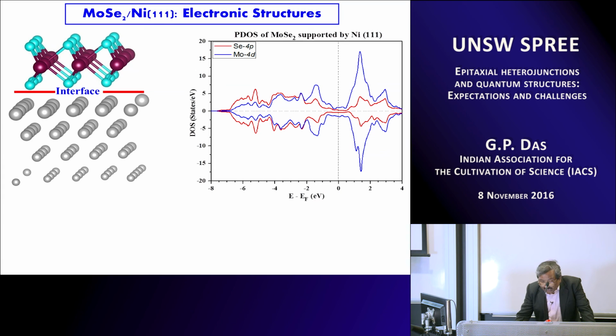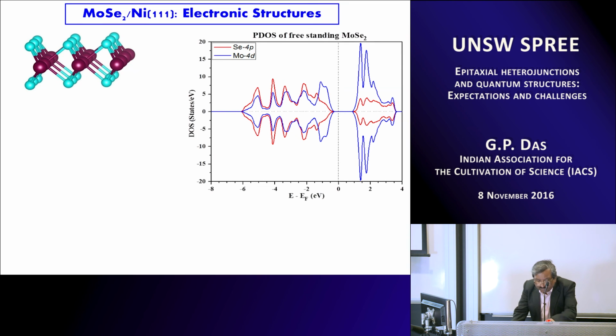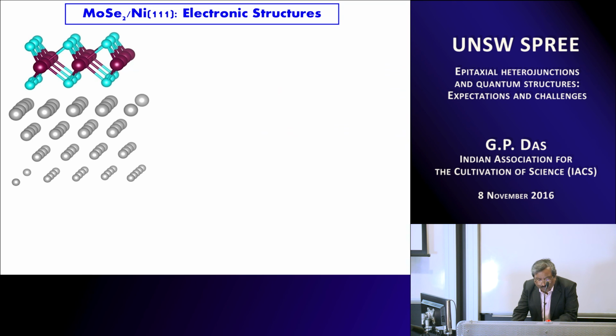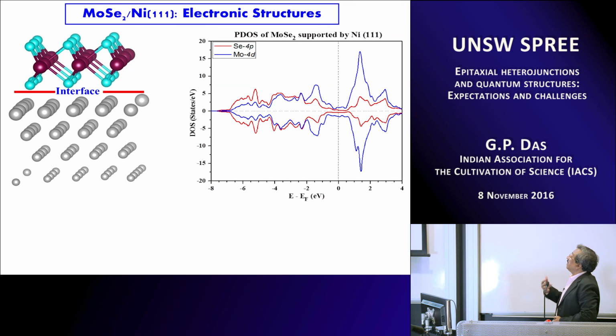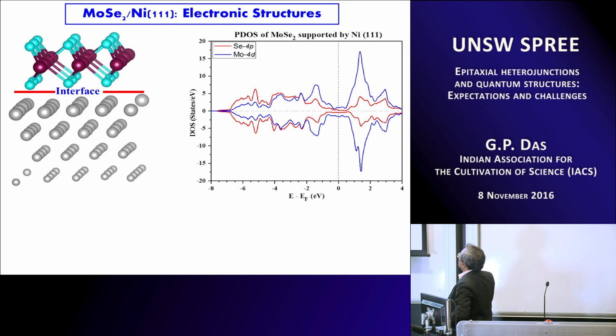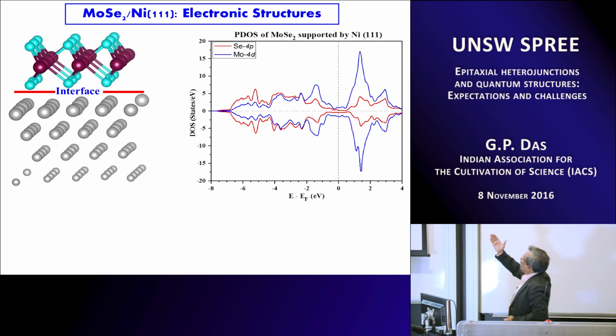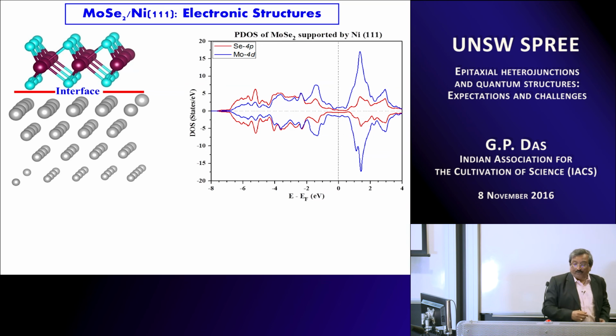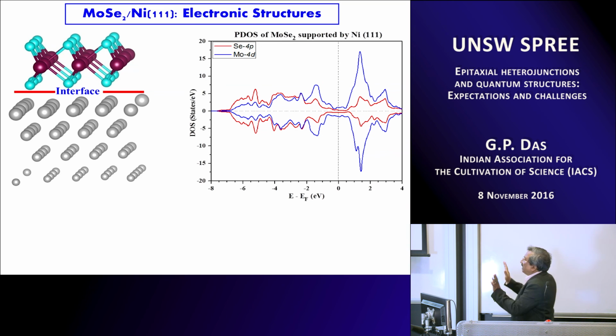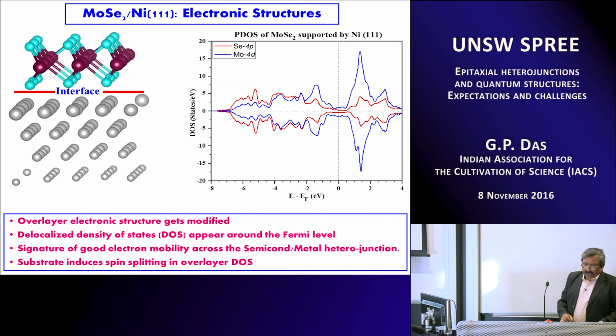You can see that there are states which are developed in the gap. You can see that clearly. There is no gap anymore. Earlier there was a pure LDA gap, whereas now as soon as you put nickel 111, there are states, and these states are metal induced states obviously, but more important is that these are not localized states, these are delocalized states. As you can see, these are delocalized all throughout. If it is a localized state, which I told you at the time of Schottky barrier height, it leads to a pinning mechanism. However, here it's a completely different physics. Here it's a delocalized state, and this delocalized density of states is a signature of a good electron mobility across the semiconductor metal heterojunction.